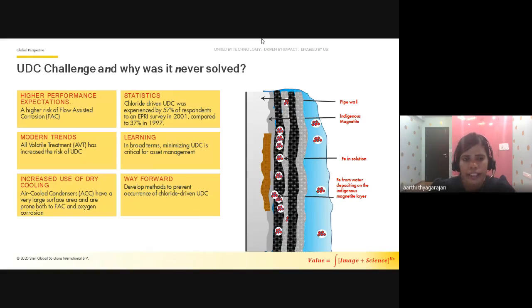Historically, there are three different types of underdeposit corrosion that have affected the evaporator tubes in high pressure steam generators. One is caustic gouging, second is acid phosphate corrosion, the third is chloride driven underdeposit corrosion. The primary cause of this UDC mechanism is related to the deposition of porous layers of magnetite particles on the water side of the evaporator tubes. The magnetite particles are typically generated by what is called flow assisted corrosion elsewhere in the system, it could be in the feed water piping or in the economizer, it can be anywhere. And then they get transported into the steam generator where they deposit onto the heat transfer surfaces.